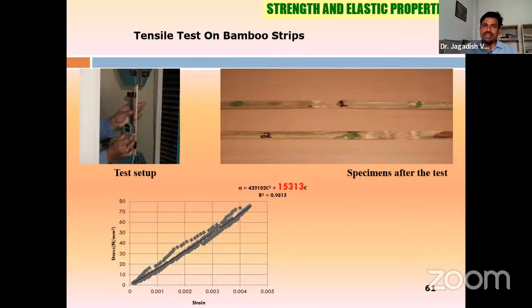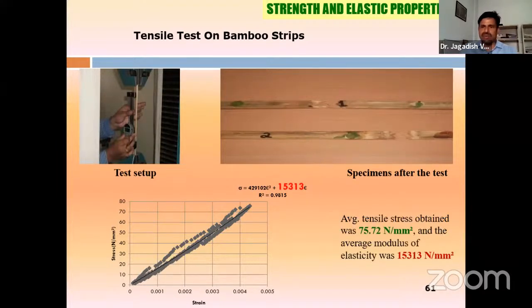Tensile test on bamboo strips was also carried out, wherein the sticks were taken and then pulled on either side. The bundle of fibers are pulled on either side. So this is what the tensile strength, what we got is around 75 MPa. And then this is the modulus of elasticity, what we got.